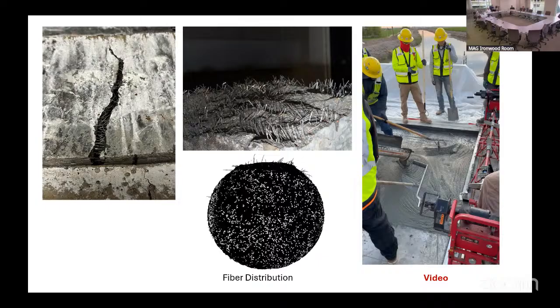It's the average number of cracks that you need to form, whether 3 cracks in a shotcrete, which has only about 4 pounds of fiber in there, or the sections that we have tested, which have 60 pounds of steel fiber. So the more fibers you put, the more these cracks get so close to each other that you can't even see it, but it has already cracked and it's deforming. So it goes back to how critical the structure is for many applications where you have environmental areas where you don't want anything to leak out. Then what we can do is put enough fibers so that the crack width is maintained. That means that permeability, the water tightness of the section, is actually addressed because the cracks are closed.